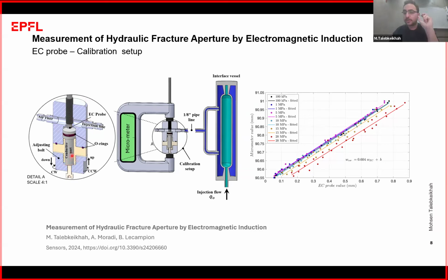During this experiment, this instrument is connected to a big micrometer. So we will have two values: one value is coming from the EC probe, and one value is coming from the micrometer. And when we plot them at different pressures, we can see that all of them have the same slope. There is a little bit of offset, and that is just because of displacement in the instrument at that pressure.